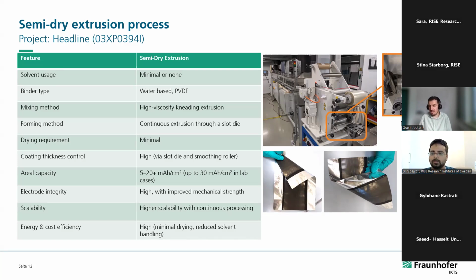Then the mixing method here is a high viscosity kneading extrusion. So during the extrusion, it's a kneading mixing method. And then the forming method of the electrode is through a slot die. Drying, as I mentioned, is minimal, since the solid content is really high.